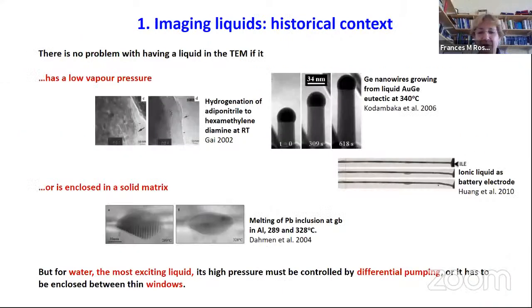Okay, so how do we do liquids in the microscope? As you know, the microscope is kept under a pretty good vacuum because you want the imaging electrons not to hit anything else apart from the sample on their way down the column through the lenses and onto the detector. So normally the microscope is held at a high vacuum. But there's no intrinsic reason not to put a liquid sample in there. There's no problem with having a liquid in the TEM if it has a low vapor pressure and won't boil away. And so many catalysts are liquid phase.